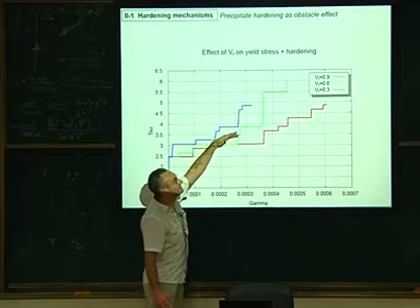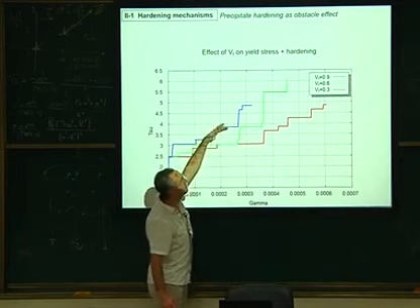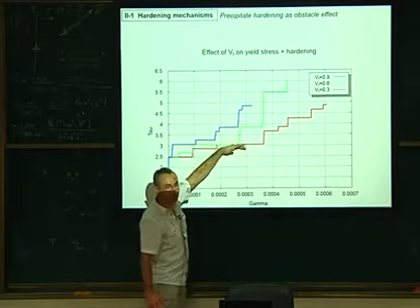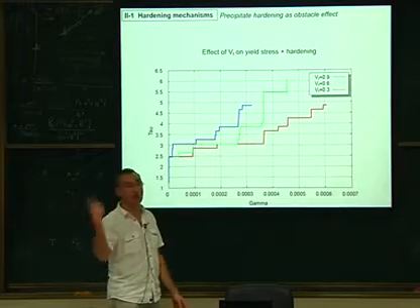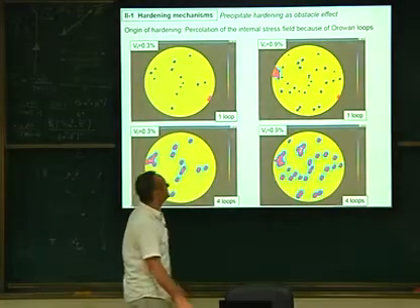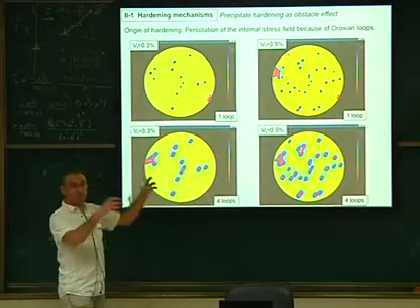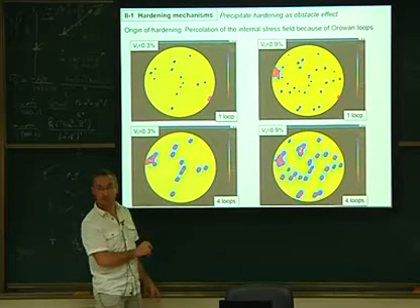Do you know why the hardening slope is much different here? For the highest volume fraction, the hardening is a lot higher than for the lowest, just because of the number of Orowan loops. Since you have more Orowan loops for the higher concentration, and you can see it here, then locally those loops create some stresses. Here what I plotted is the internal stresses due to the dislocations.